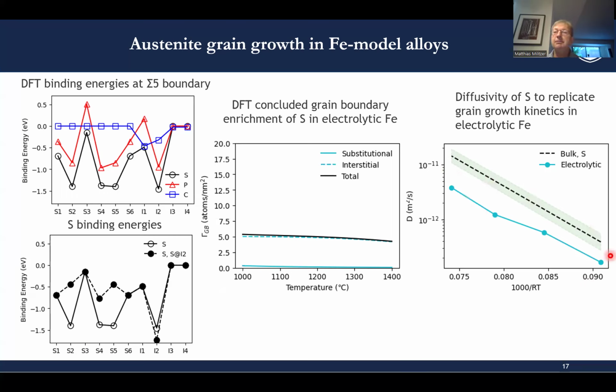This is maybe at first look a little bit surprising, because we always think that grain boundaries are fast diffusion paths. But there's increasing evidence that it's not true for interstitial elements. And since interstitial sites are involved here, it's maybe quite reasonable that the diffusivity of sulfur across the grain boundary is smaller by a factor of 2 or so than the bulk diffusivity.